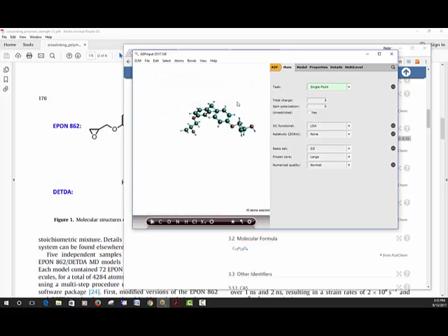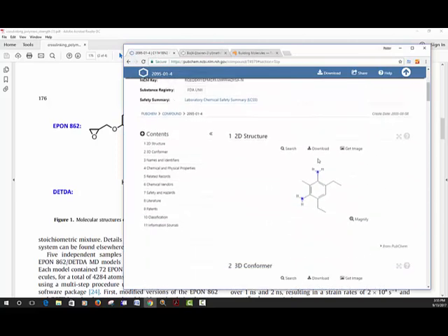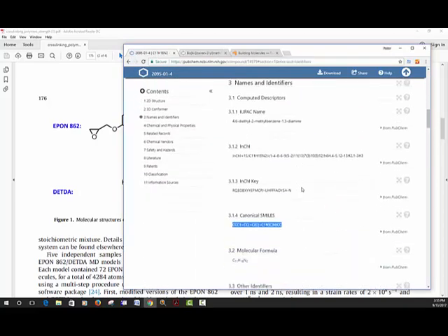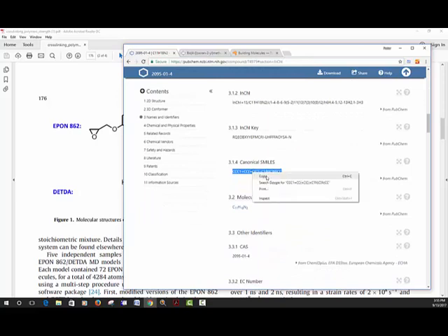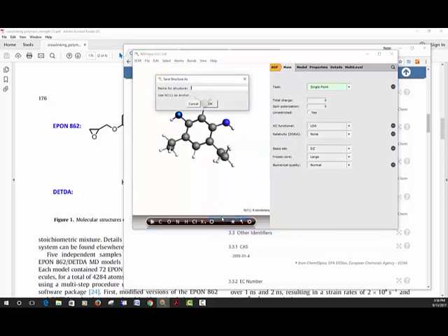And then we repeat the procedure for our cross-linking agent. So again, you can just look that up in a search engine, find its SMILES or its InChI string, paste that directly into ADF input. And again, if we want to start building polymers, we remove the two hydrogen atoms here, so it can start forming bonds with the various polymer strands. We select one of those nitrogen atoms as an anchor point, and we save that as monomer DETDA.